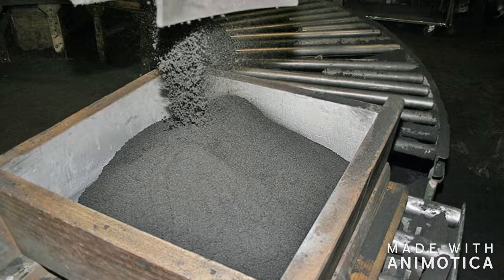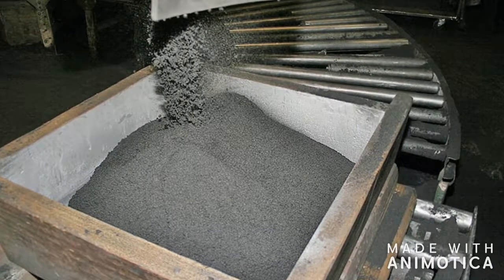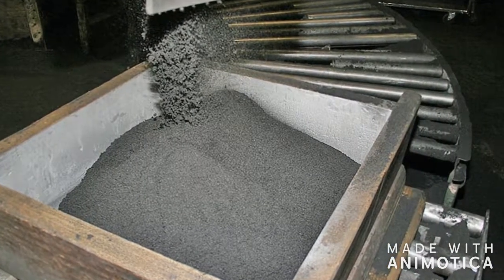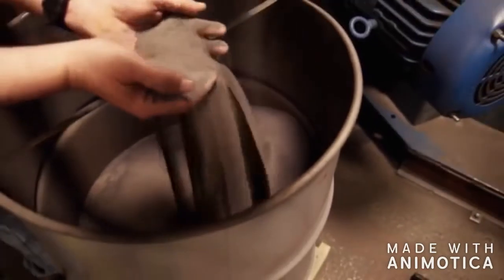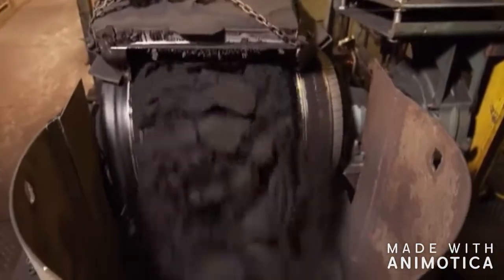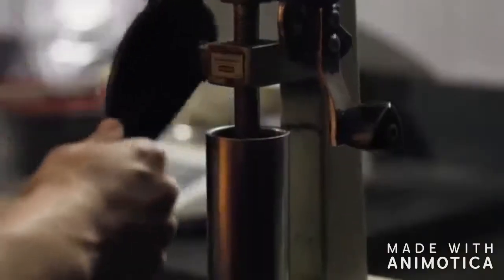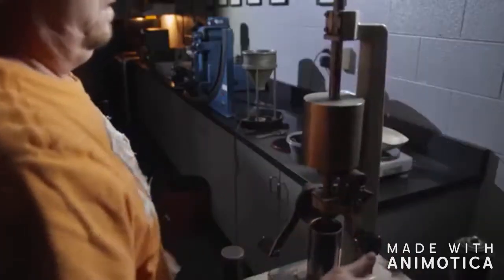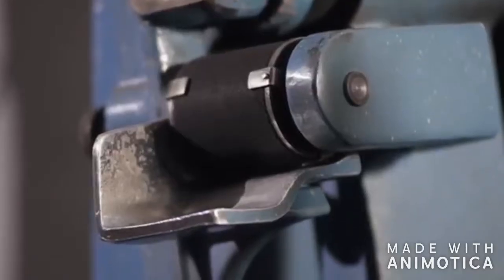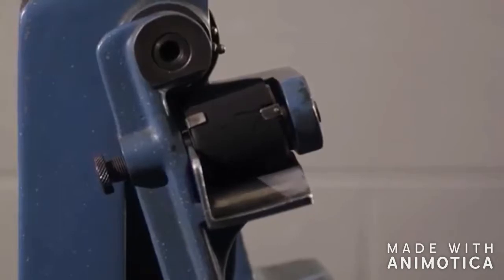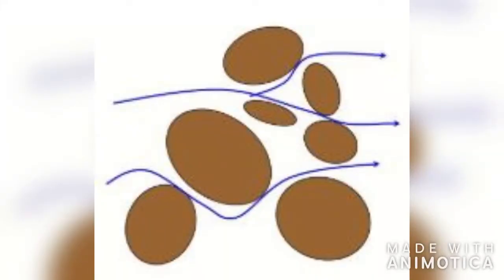In addition to pouring the metal at the right temperature, making the sand mold itself is a crucial step in the casting process. A mixture of sand, bentonite clay, and water is mixed together in a large mixing mold called a muller. The mixture is then compacted together into a dense mold which must withstand a pressure of 29 to 32 psi. Within this pressure range, the sand mold not only exhibits good enough permeability to allow the air within the mold to escape as the molten metal enters, but can withstand the stresses caused by the solidification of the molten metal.